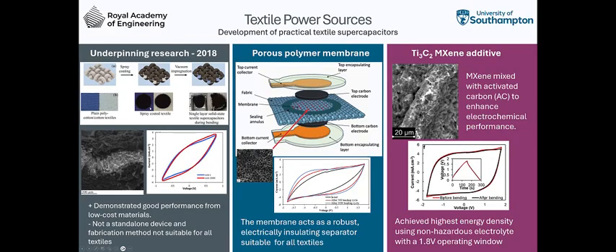And we simply spray coat this onto the textile. And by controlling how we spray coat it, we leave a region of the textile in the middle uncoated. And this acts as the separator between the two electrodes. And then you simply add your electrolyte and you have a very well-performing supercapacitor with excellent cycling stability. So this graph just shows the first cycle and the supercapacitor performance after 15,000 cycles. So it's very, very stable.